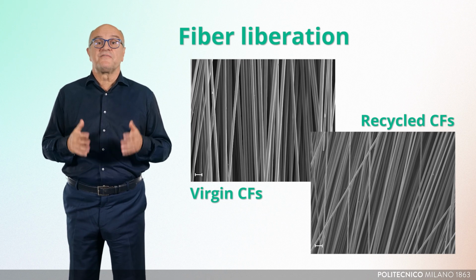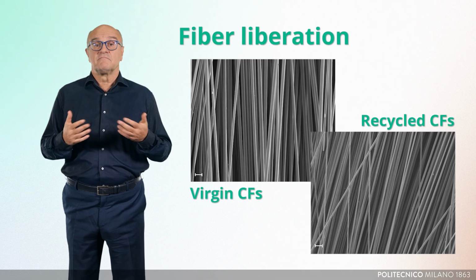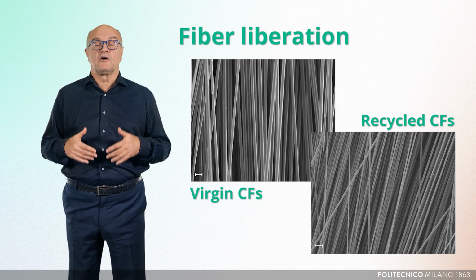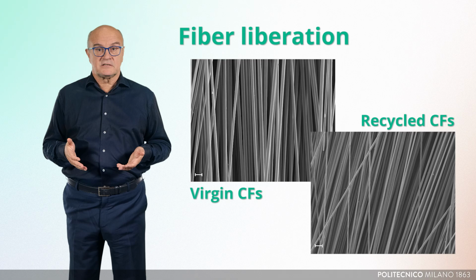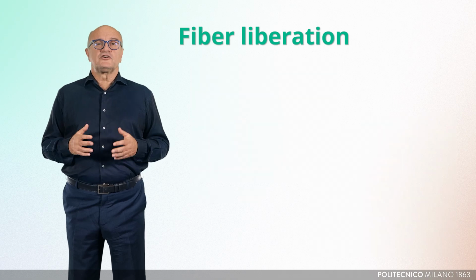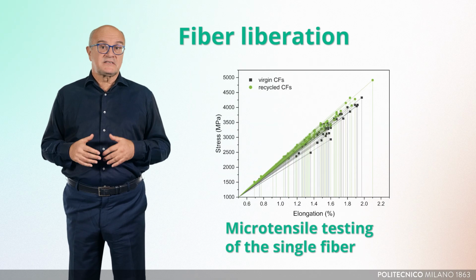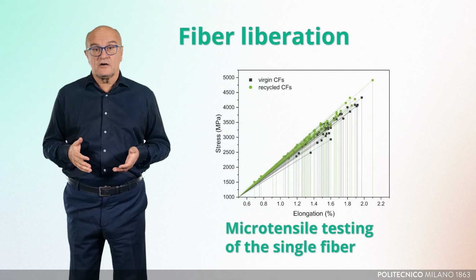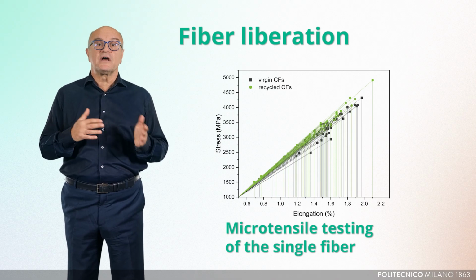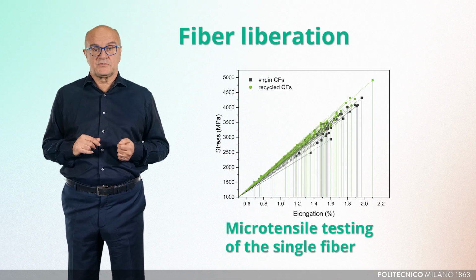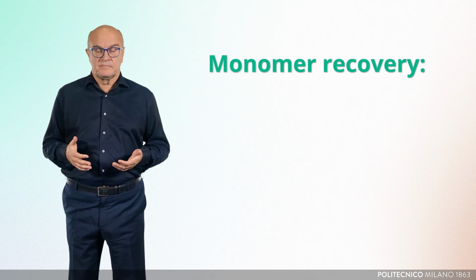The purity of the fibers can be assessed, for example, by electron microscopy or by thermogravimetric analysis. The retention of mechanical properties can be assessed by microtensile testing of the single fibers before and after the recycling process. As a second point, it also allows the monomer recovery.